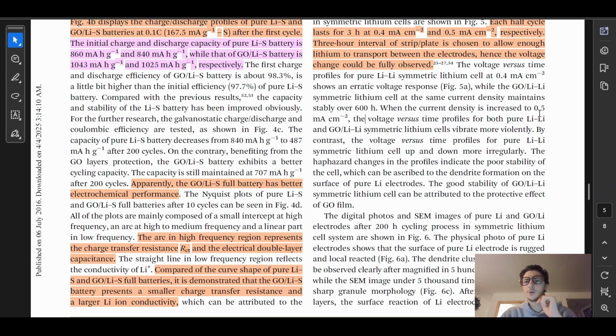When the current density is increased to 0.5 milliamps per centimeter squared, the voltage versus time profiles for both pure lithium and graphene oxide lithium symmetric cells vibrate more violently. By contrast, the voltage versus time profiles for the pure lithium symmetric cell go up and down more irregularly. The haphazard changes in the profiles indicate the poor stability of the cell, which can be ascribed to the dendrite formation on the surface of the pure lithium electrodes.